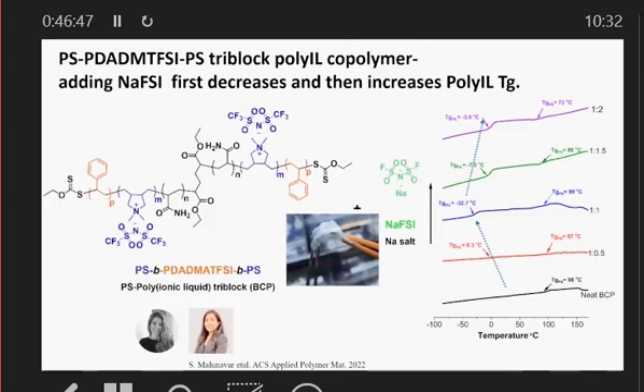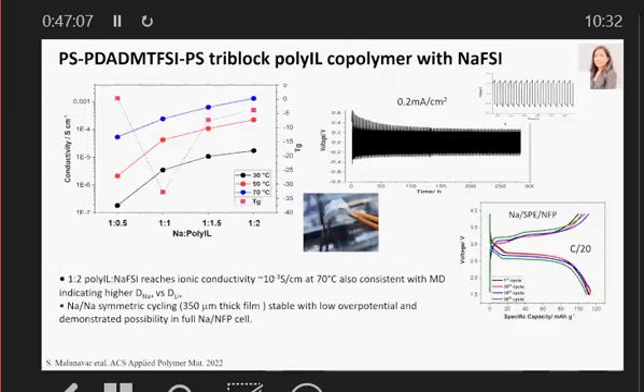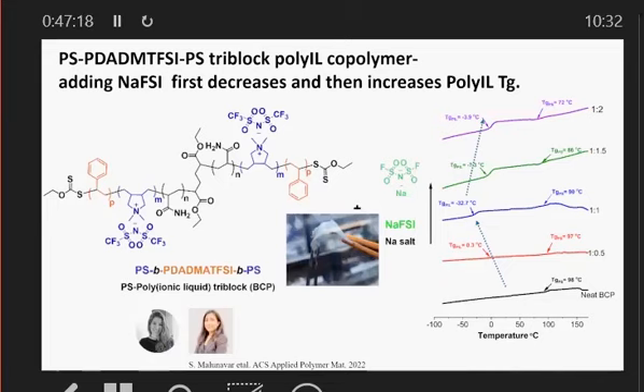We used this material with sodium in that case, because Sneha's project was a sodium-based project, and she added different amounts of sodium FSI salt. We found, as with the previous data we showed early on, that the Tg did go down, although there was this parabolic type behavior again in this system, interestingly, which is a mixed system. Sneha then looked at the conductivity, and we went as high as 70 degrees because, if I go back to here, the Tg of the second block, the polystyrene block, because it was low molecular weight, was actually affected by the Tg of the other block. So Tg went down in the system.